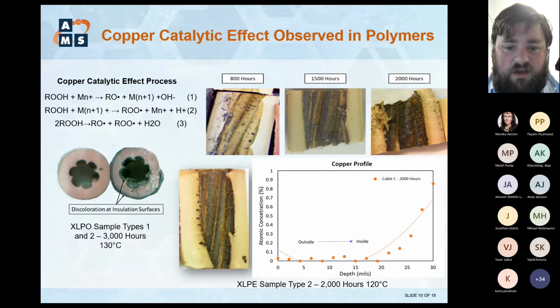In the EDS data, you can actually see that at that interior surface, you are getting copper migration into the insulation that's driving the interaction. And then the left image actually is an insulation tube that was pulled in tension to do tensile testing. You can actually see the cracks that formed at that interior surface because of that catalyzed oxidation process that's happening.